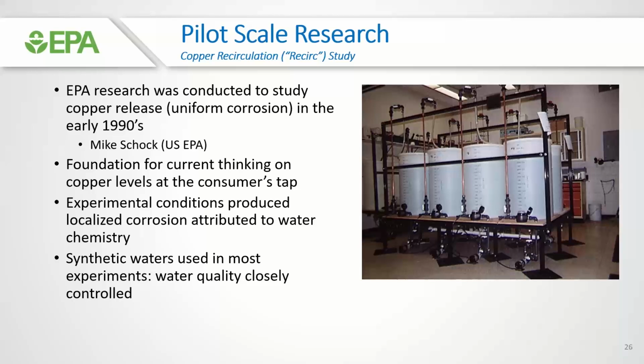Like soluble copper levels in uniform corrosion, you can actually do some piloting as well. It's just a different thing. You're not necessarily interested in copper levels because, as I said before, they're low. But what you're doing is spending time looking at the pipe surface itself instead. So you're looking for that pit cap to form. And so here we have some recirculating experiments. We've taken new copper pipe from the hardware store and just put it on a unistrut frame, and had a utility run water through it and periodically pull. We had little union connections, pulled them off, looked at the pipe and looked for the pit caps.